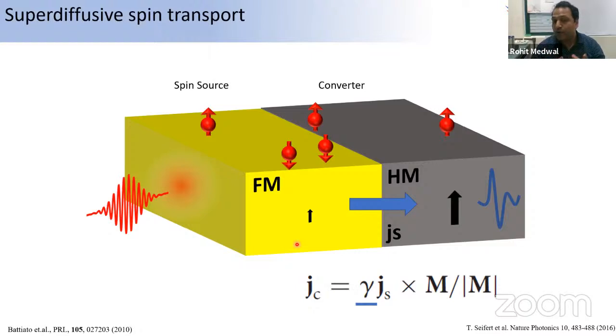As I explained, we have the spin Hall effect and inverse spin Hall effect, where we can convert spin current into charge current using the inverse spin Hall effect, and convert charge current into spin current using the spin Hall effect. So here we are pumping the spin from the ferromagnetic material to a heavy metal by optical excitation. So we can use the spin Hall effect of the heavy metal to convert this spin current to a charge current. One point. Second point is, what is the magnetization direction of this ferromagnetic material?